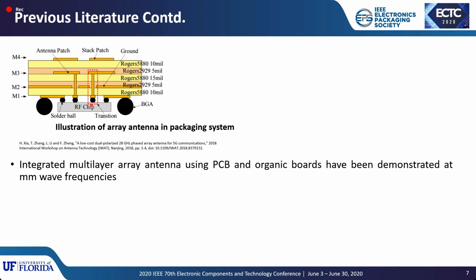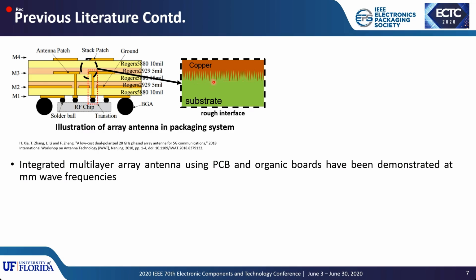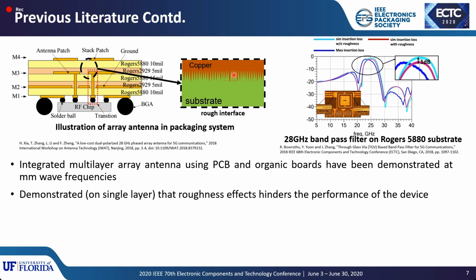Whereas if we look into the multi-layer patch antenna stack-up, as you can see, we have different layers with different feeding line architecture and through vias, which consists of an RF chip on the bottom and which is also integrated with the ball grid array packaging type. If you look closely at the interface between the Rogers board and the substrate, you can clearly see that there is roughness at the interface layer. And also, in one of the previous works, a 28 GHz bandpass filter on Rogers 5880 substrate, you can clearly see that there is an additional 1 dB insertion loss at nearly 25 GHz due to the roughness effects of the substrate. Therefore, the roughness effects hinder the performance of the device at high frequencies.